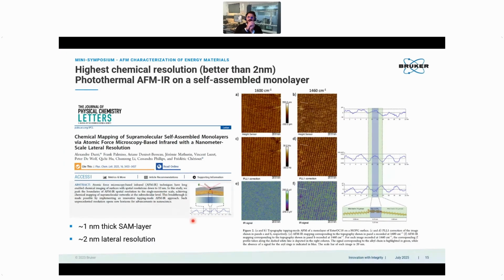So as I mentioned, the main inventor, if you want, of the idea of using atomic force microscopy to measure the photothermally expanded surface of a sample is Alexander Dazzi. And we collaborate very closely, and we work with him on this technology. So Professor Dazzi published, I think in 2023, so earlier this year, this very nice result. And I was in the lab when this was popping out on the screen. So what you see in here is a surface of self-assembled monolayers. And it's an extremely thin surface, like a single monolayer.